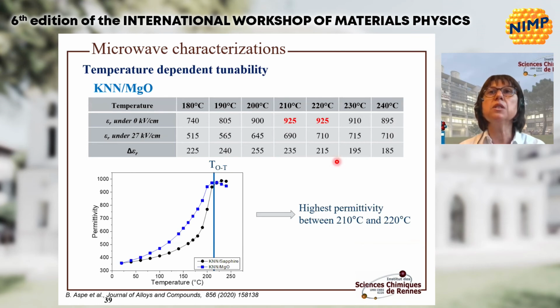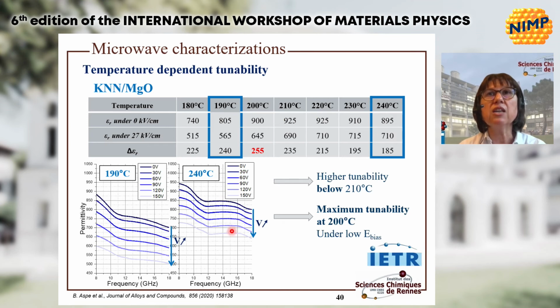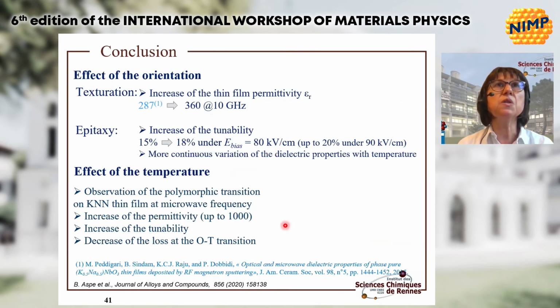If we have a look now at this permittivity, we can see the maximum around 210 and 220 degrees. But what about the tunability, that is the evolution with the voltage? We can see that the higher tunability is obtained just below the transition, with a maximum of tunability that has been measured at 200 degrees C, here with a variation of epsilon of 255. That means that in this system, it has been possible to tune the tunability, especially with composition and also with the substrate itself. We have also measured the transition, the pseudomorphic transition, sorry, at high frequency at 10 gigahertz on these thin films.